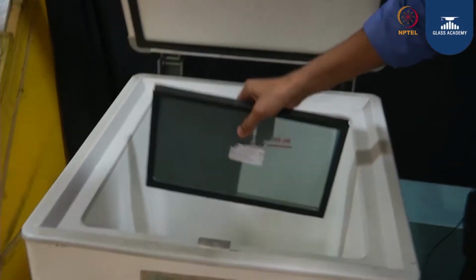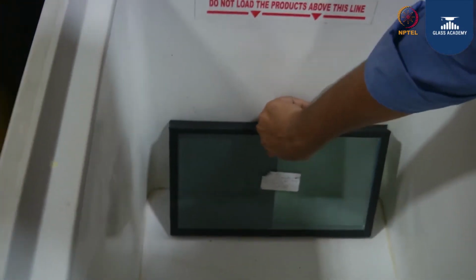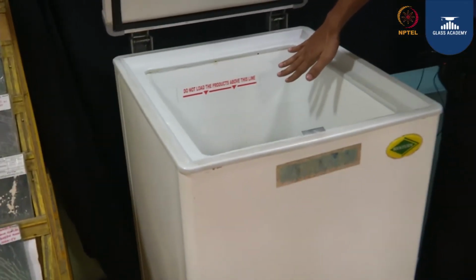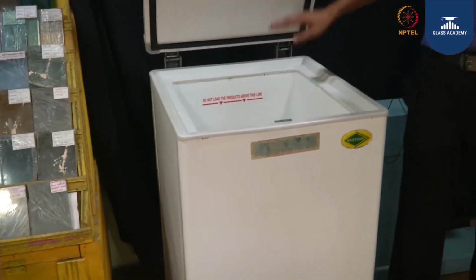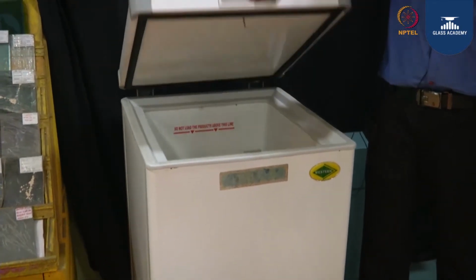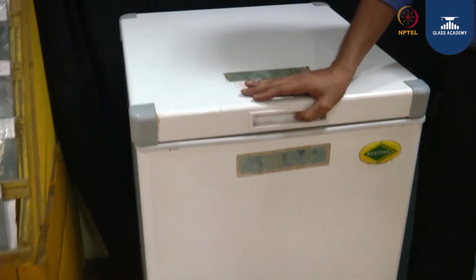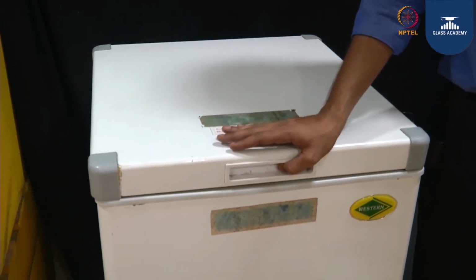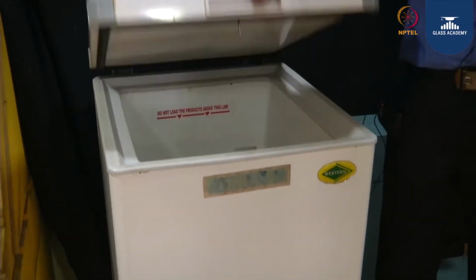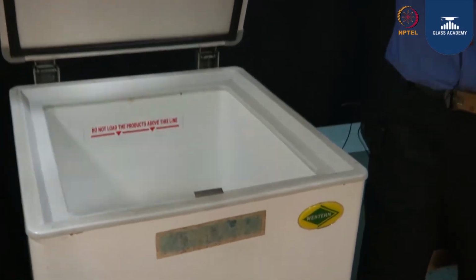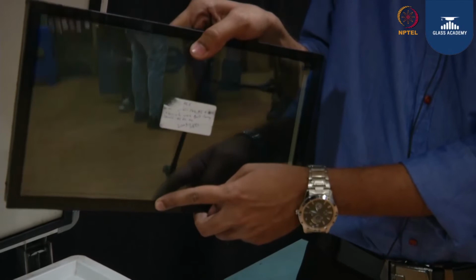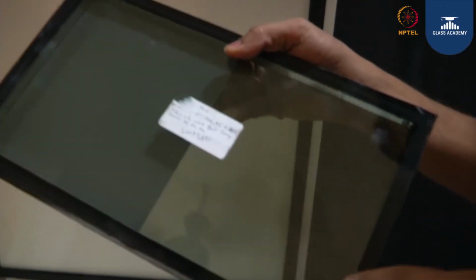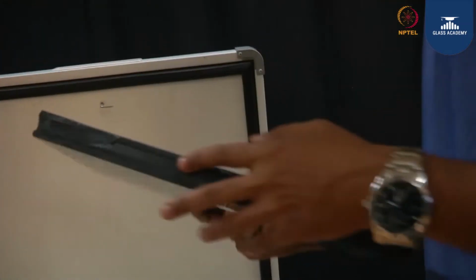We'll be taking a DGU sample and placing it inside the freezer at minus 18 degrees centigrade for 2 hours. Through this test we are making sure that under extreme negative temperatures how the DGU is going to perform. If any condensation is there inside the DGU, we check whether the desiccants we saw on the shop floor are able to absorb the moisture, whether there is any discontinuity in the butyl, and whether the silicone is properly sealed or not.